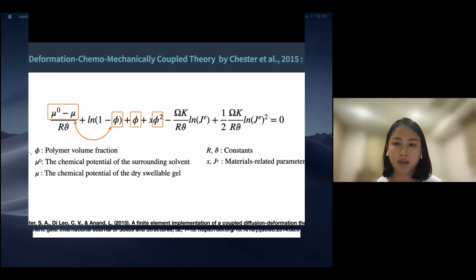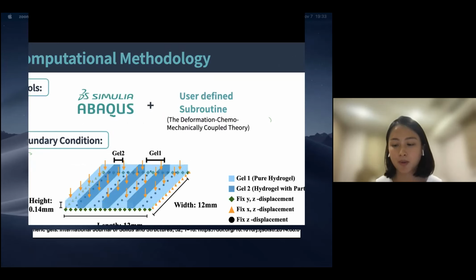So as the time increases, the gradient of the chemical potential will be lower, and the polymer volume fraction will be lower as well. We use the finite element package Abaqus, combined with the user-defined element to enable the theory I just mentioned in the previous slides, and reproduce diffusion in the polymer and the extremely large deformation of the hydrogel.